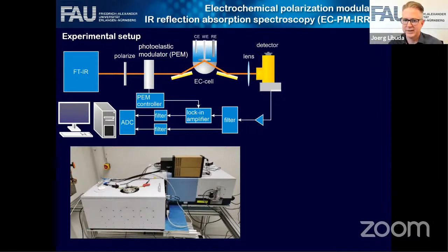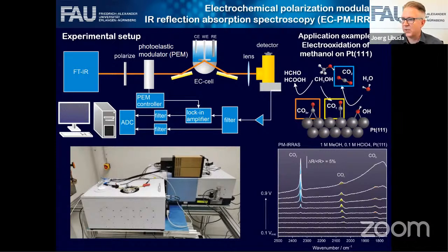At the same potential. Yeah, so this is possible. This really works. This example here is for the methanol oxidation, where you can see species adsorbed on the surface. So methanol oxidation leads to CO adsorbed on the surface, and here you see CO adsorbed on the surface during methanol oxidation taken by PM-IRAS. But one thing that you can already see from these spectra is that typically the drawback is that the signal-to-noise ratio is worse as compared to conventional infrared spectroscopy.